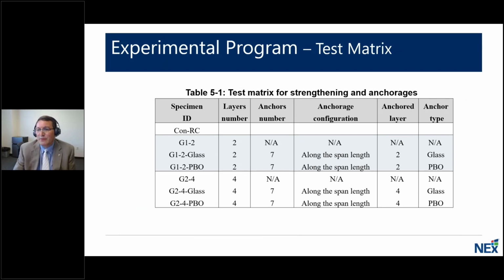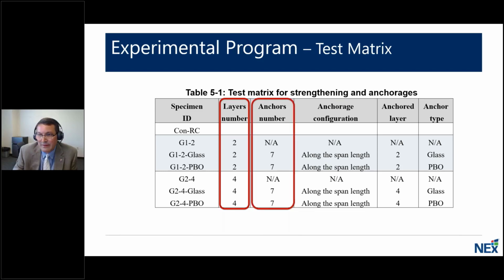First, in terms of the test matrix for this work, it included a control specimen shown here, as well as two specimens, one with 2 plies and one with 4 plies. Recall that 4 plies resulted in a debonding failure in flexural testing earlier, while 1 and 2 plies, remember the 2-ply test was done at the University of Miami, both failed in a slippage failure. So what will this tell us about slippage failure and debonding failure and the necessity for using an anchorage system? Again, this gives us a detail on the number of anchorages, and the two different anchorage systems were a spike anchor as well as the PBO anchorage system we tried in this particular work.